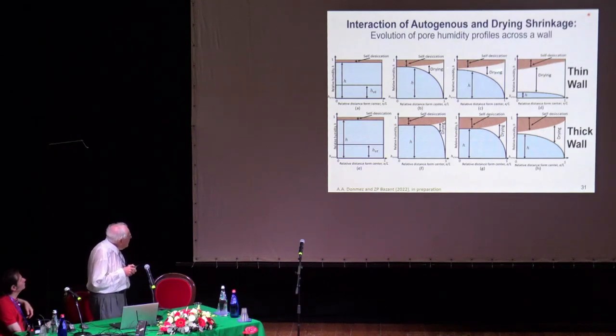So in a thin specimen, it is different than in thick walls, where you maintain high humidity for a longer time, and then self-desiccation proceeds, and you get this kind of picture. So this has to be included in the predictions.